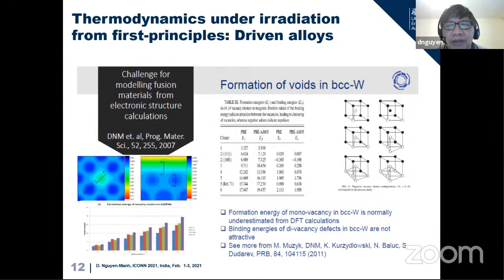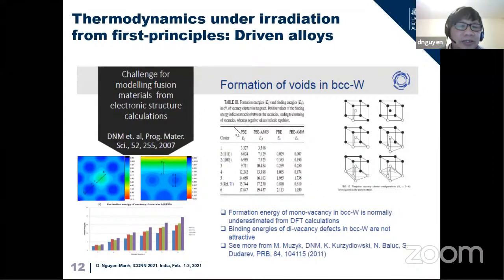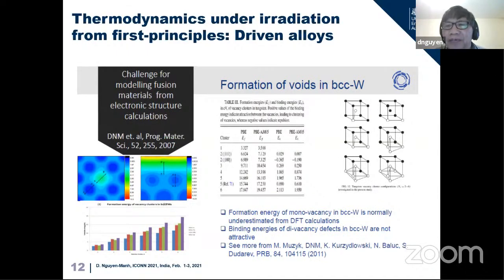So we need to go beyond the PBE functional and treat the electronic charge around the vacancy or cluster of vacancies inhomogeneously. We have done quite a lot of work on that and realized from DFT calculation that the binding energy between two vacancies is negative, meaning that they are not attractive. So from classical theory, it is not easy to form a void from a divacancy. So we need to go to vacancy clusters. That is what we try to do, and we find that the binding energy of the vacancy cluster starts to build up from three vacancies, four vacancies.